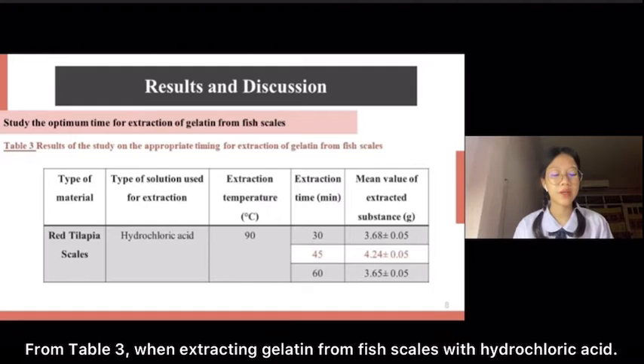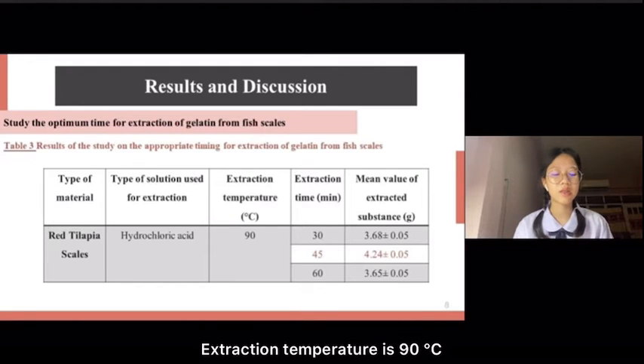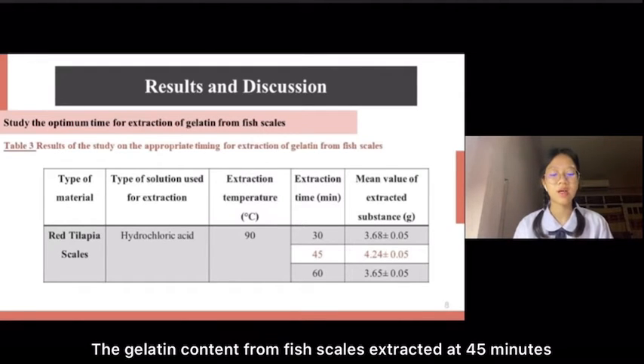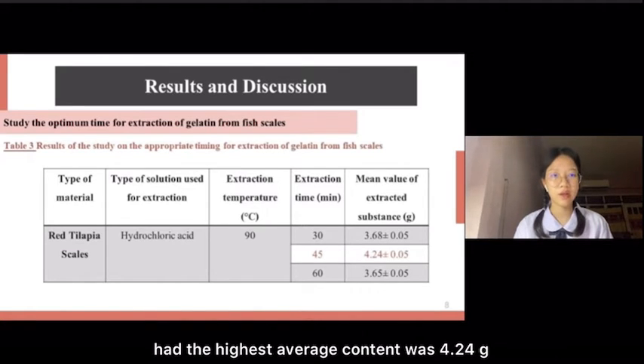From Table 3, when extracting gelatin from fish scale with hydrochloric acid at an extraction temperature of 90 degrees Celsius, the gelatin extracted at 45 minutes had the highest average content, 4.24 grams.